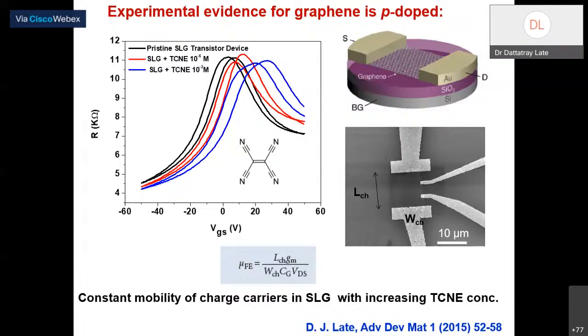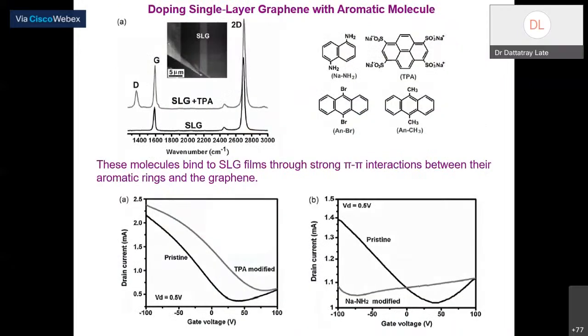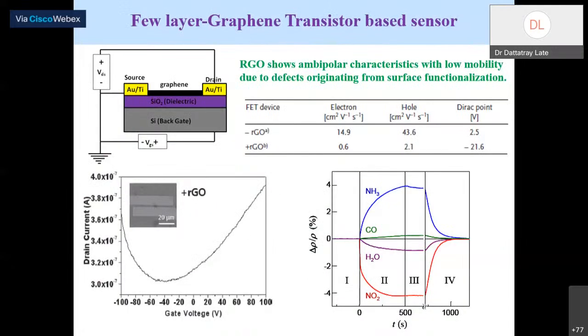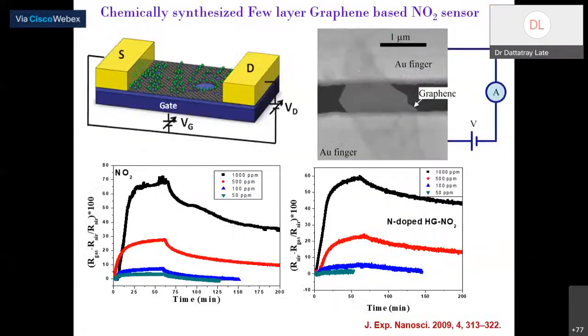So this is the experimental evidence that we can make graphene either p-type or n-type. These are experimental results found on graphene with various molecules, and again the devices are based on transistors, and we found that there is a shift in the device characteristics because of the very strong pi-pi interaction between aromatic rings and graphene. A lot of physics and chemistry happens on the surface of graphene. Again, we have few-layer graphene or reduced graphene oxide, and we have tested them for applications like sensor application.